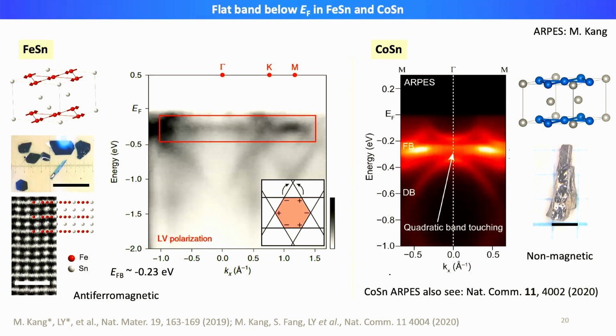And those are a few different crystals I've grown during my PhD. I think you can see from this transmission electron microscopy cross section of the iron tin crystals that there are two different layers in the structure. The more densely packed atoms correspond to the kagome layer, and the larger atoms correspond to the spacer layer of the tin here.